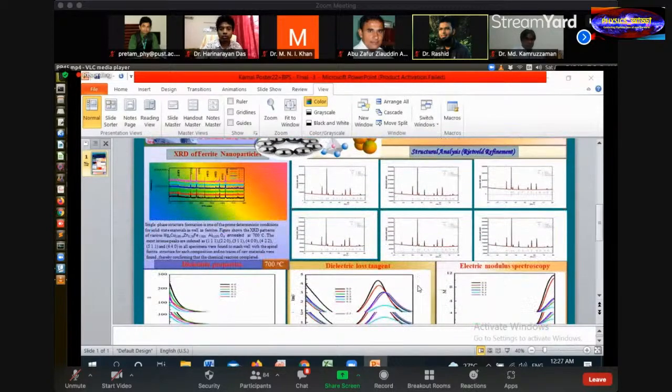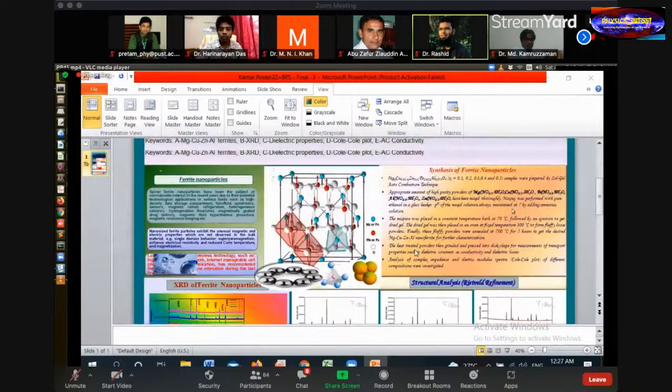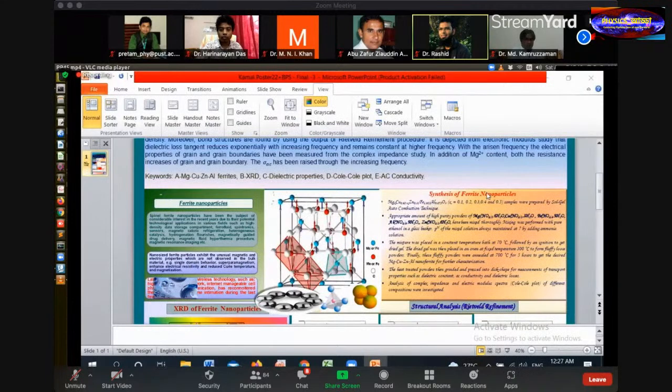Now the discussion. I will discuss the synthesis. Nitrates of raw materials are weighed and mixed in ethanol, then the mixture is dried and combusted to obtain powder, annealed at 700 degrees centigrade for 5 hours, and ground to obtain magnesium, copper, zinc, aluminum ferrite nanoparticles.